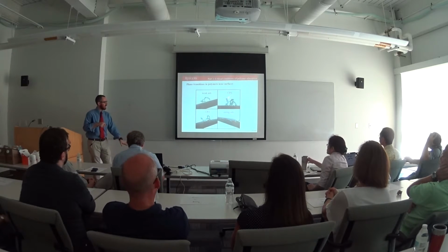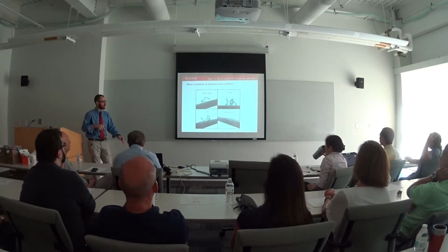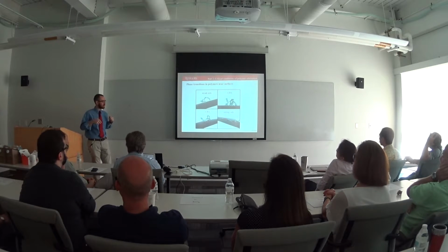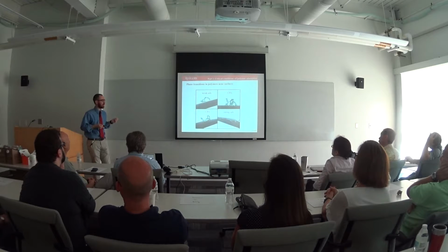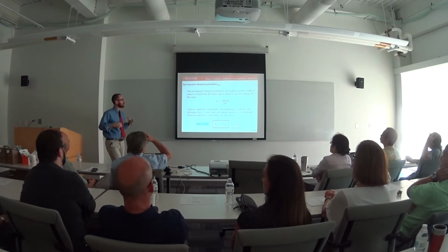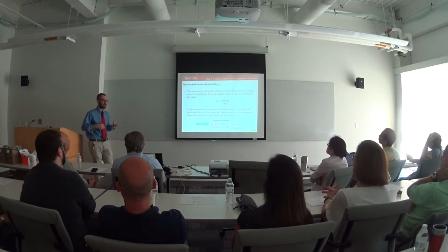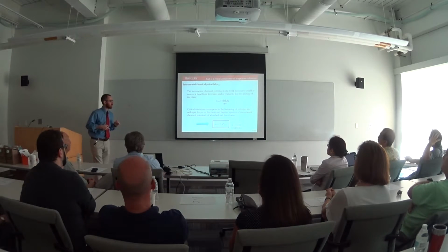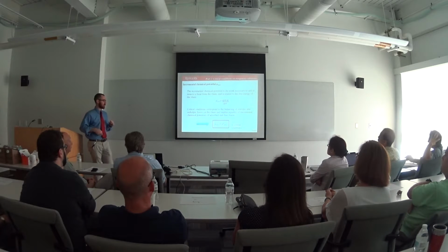And there is a case in which your solvent conditions are such that the chain is equally likely to be adsorbed or not adsorbed. And this is called the critical point of adsorption, the CPA. In order to study the CPA, we introduced something called the incremental chemical potential criterion. The incremental chemical potential can be thought of as the work necessary to add or remove segments of our chain from the end of the chain. And it's related to the free energy of the chain, as shown in this equation.